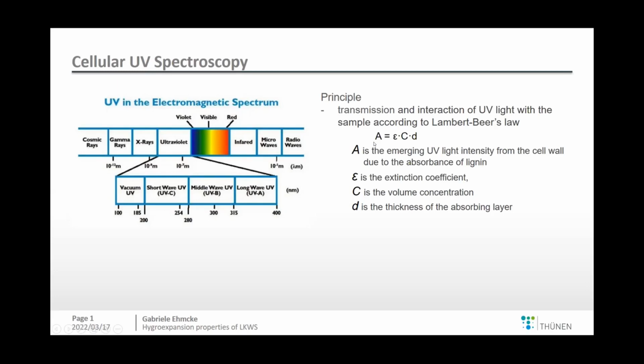The principle of this technique is the transmission and interaction of the UV light with the sample according to the Lambert-Beer law. We heard already something about Johann Heinrich Lambert in the DIC presentation of Václav. So here we have the combination of Lambert and Beer. And it says that we have A as the absorbance of UV light that comes from the cell wall due to the absorbance of lignin. Then we have the extinction coefficient and the volume concentration, as well as the thickness of the absorbing layer.